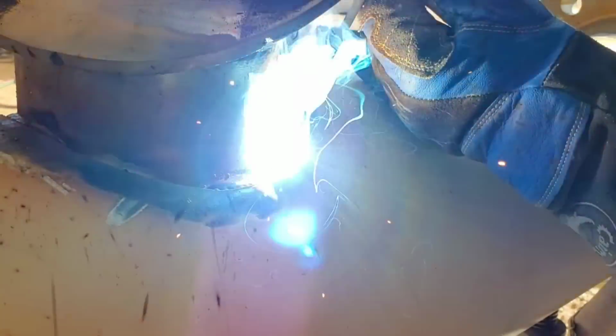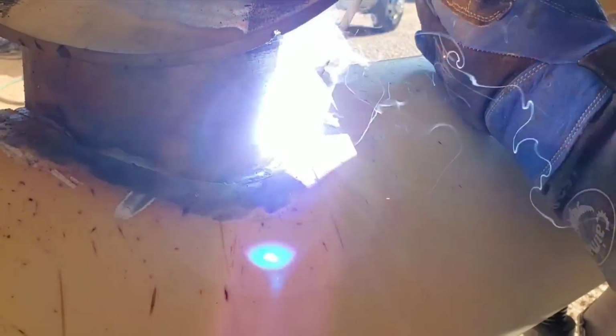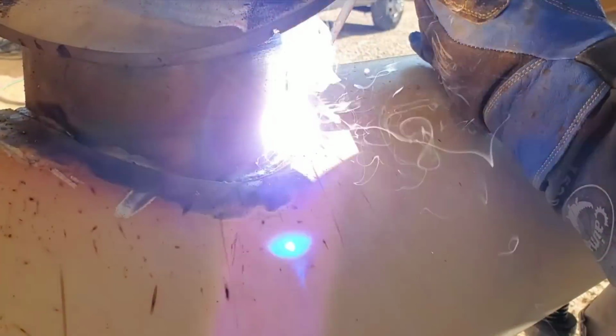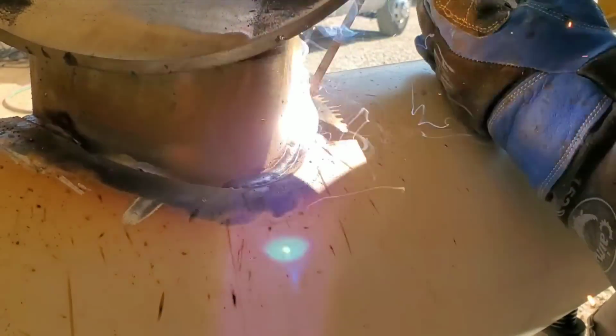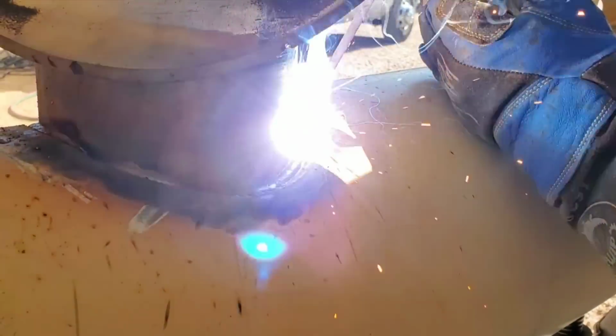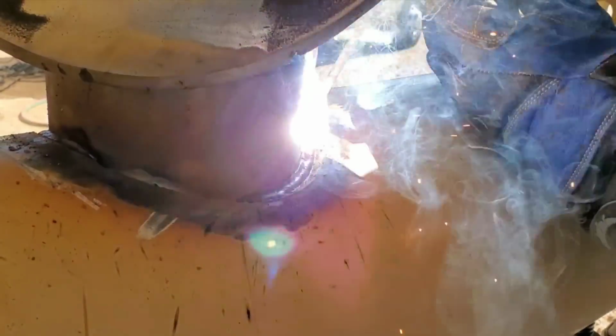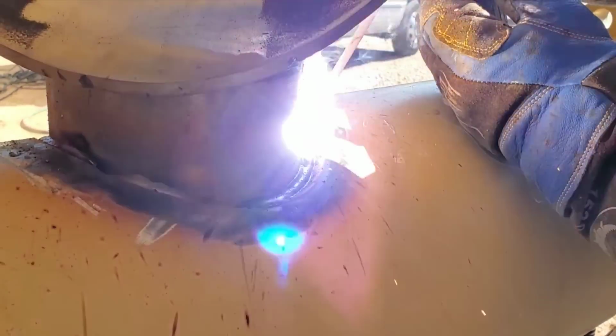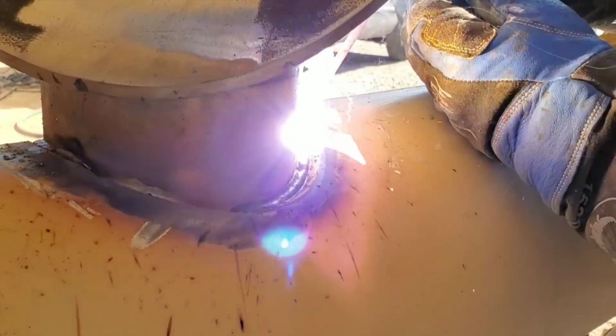I weld it out in quarters. I weld from the bottom up here, and then I'll jump over to the other side, weld it from the bottom up, and then jump back over to this side and grind out my start to make sure it's good and not dirty, because you don't want to be trapping slag, and you definitely don't want to be putting porosity into this part of the weld at all.